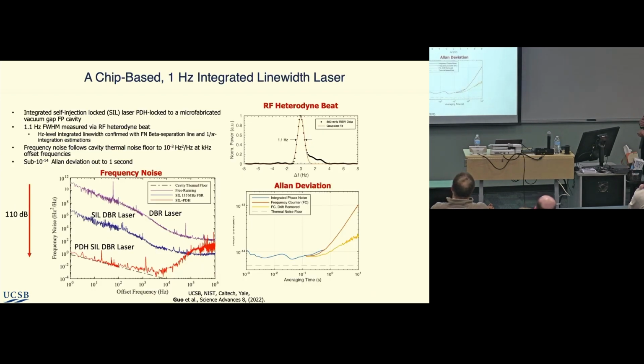So the laser noise by itself is here in purple. When we lock it to that cavity, just tuning it so it locks into the range, we get say 50 dB noise reduction. When we lock to this high Q cavity, we get another 60 dB of noise reduction. So this laser has an integrated linewidth of about 1 hertz, and you really do get 110 dB noise reduction at low frequencies.